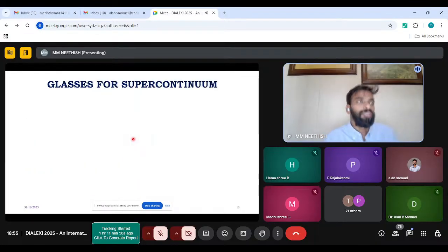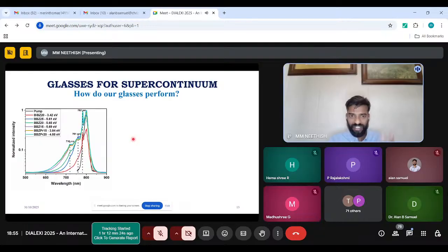So now, after preparing the glasses, we decided to study them. I did it for my PhD also. Dr. Alan B. Samuel also did similar things. We prepared glasses, and we decided to study the supercontinuum generation from these glasses. So we put it in front of the femtosecond laser, and we record the generated spectrum using the spectrometer I have shown in the experimental setup, and we see some spectra.